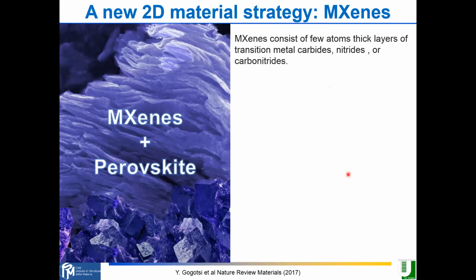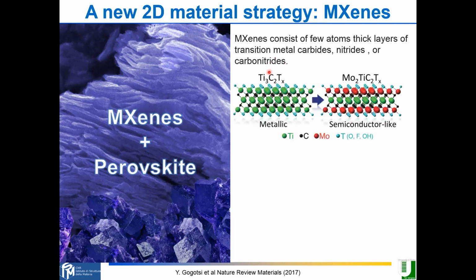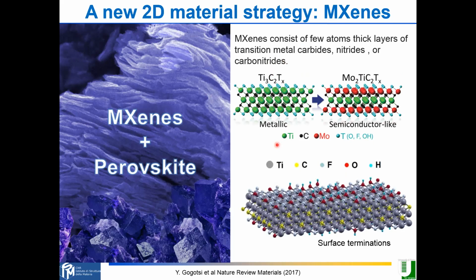Recently, we were trying to find a different idea for the use of 2D material that can also impact the perovskite, and we were focusing our attention on MXenes. MXenes are 2D materials made of a few layers of transition metal carbides, nitrides or carbonitrides. The most famous is, for example, titanium 3 carbon 2, Ti3C2. In this kind of material you can change atoms, so you can also change the metallic or semiconductor characteristics. But very important, you have a surface, and you can functionalize the surface, typically with hydroxyl groups, oxygen, or fluorine groups. It depends on the chemistry you use for getting these materials. So this is very important because you have a surface that can be functionalized.